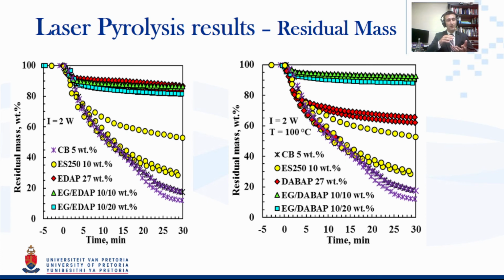That the 10 weight percent expandable graphite on its own was not that much better than the neat material in a small scale pyrolysis test, but in the mixtures, in the binary systems, we achieved some exceptional results in that our mass loss actually went to only 20% from a previous point where it went to 5% or 10% remaining at the end of the entire thermal event.